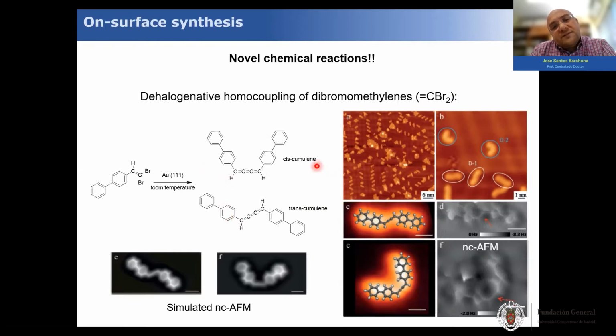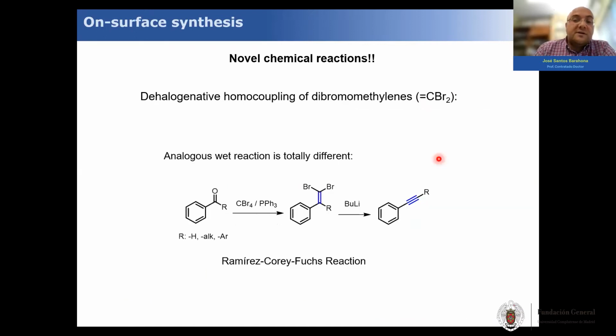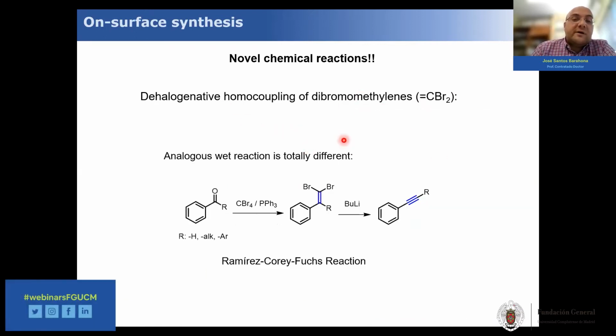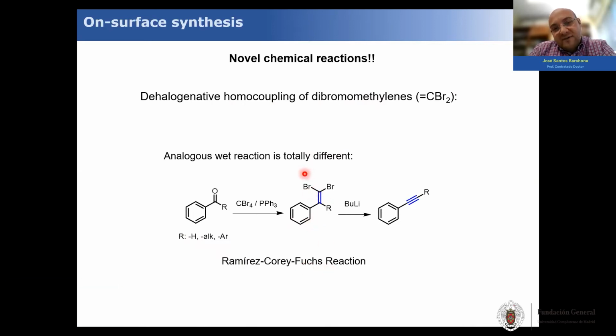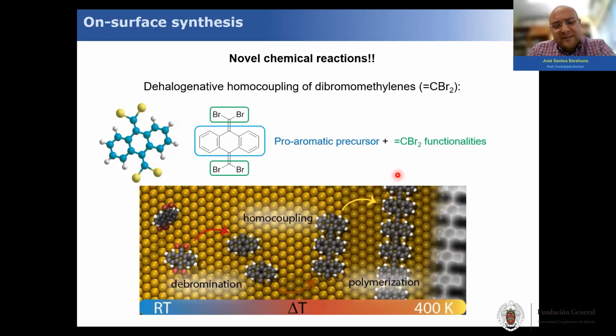They have this mixture of cis and trans cumulene. This transformation is counterintuitive with conventional chemistry, where this procedure is better known as the Corey-Fuchs reaction. When you have this functional group and you dehalogenate the bromines using BuLi, what you get is an alkyne rather than the butadiene, sorry, the cumulene.